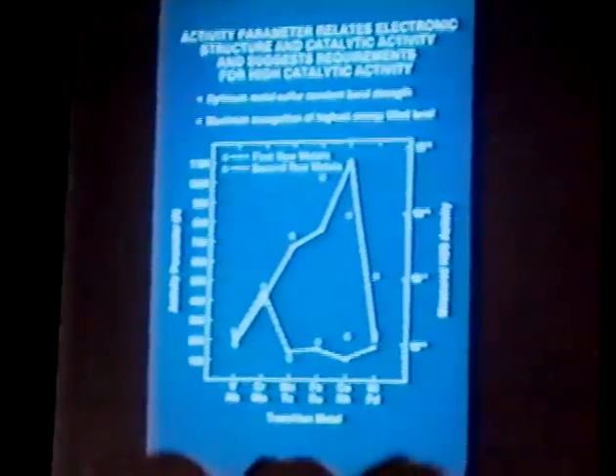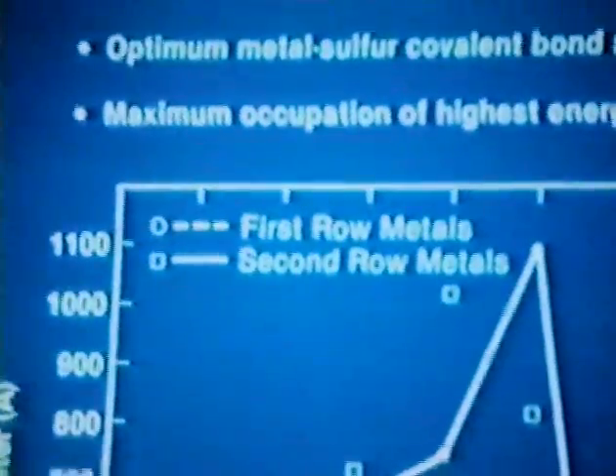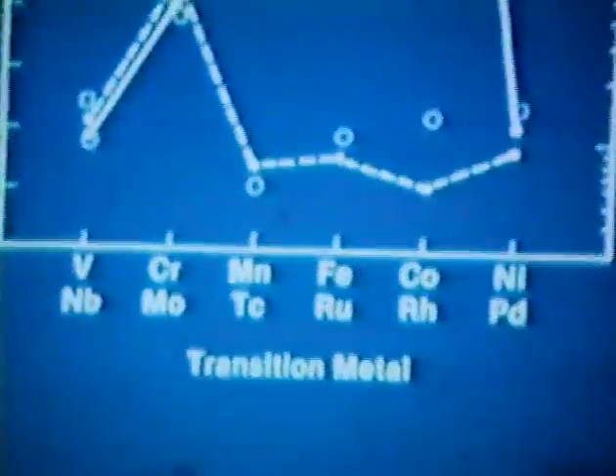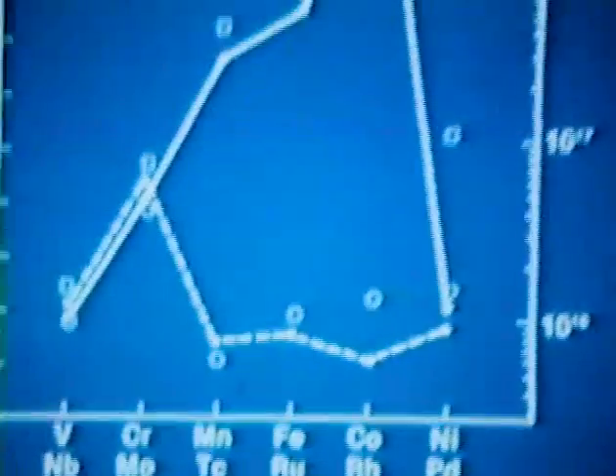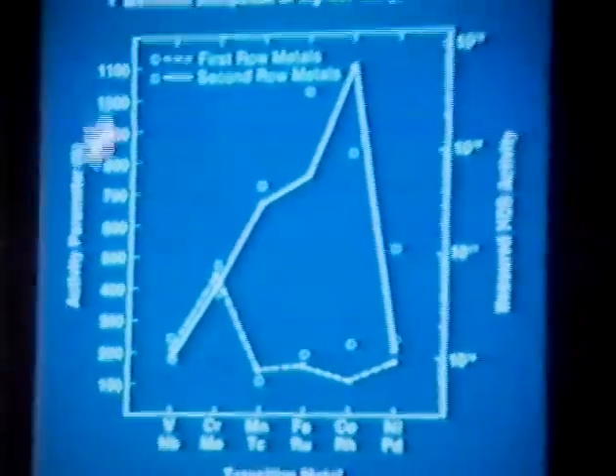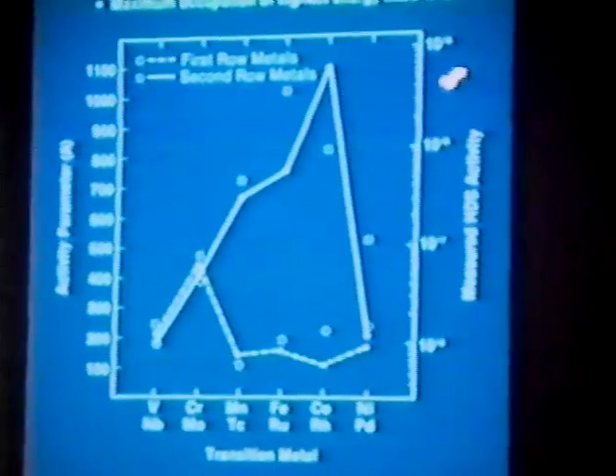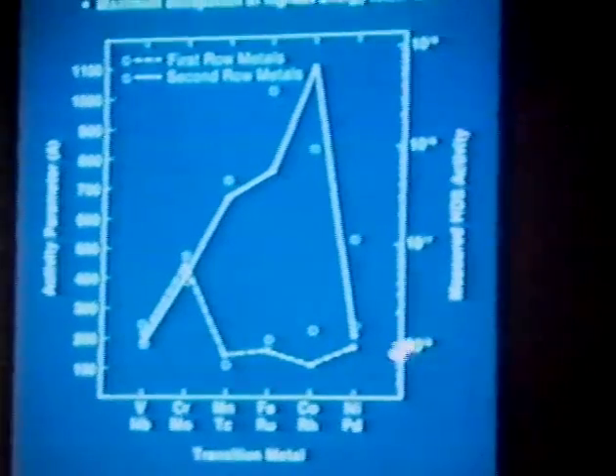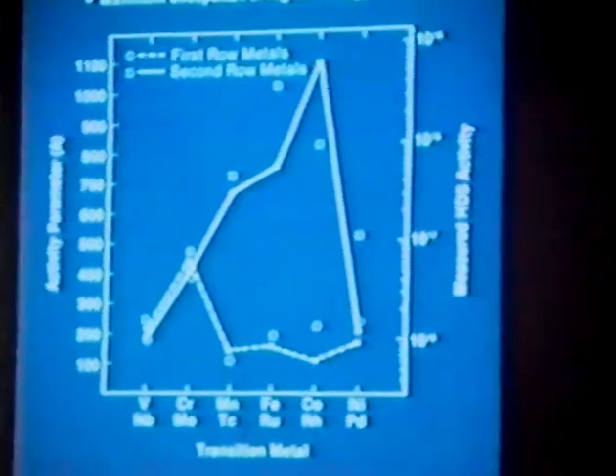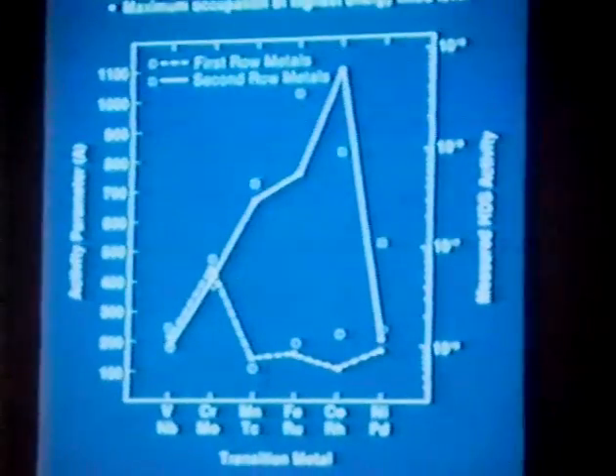Here is a result showing experimental points and the calculated points for the first and second row transition series that we've calculated. We have on the left here the activity parameter, and on the right, scaled appropriately, the HDS activity that I've shown you before. You can see that the most active catalysts have this optimum metal-sulfur covalent bond strength.